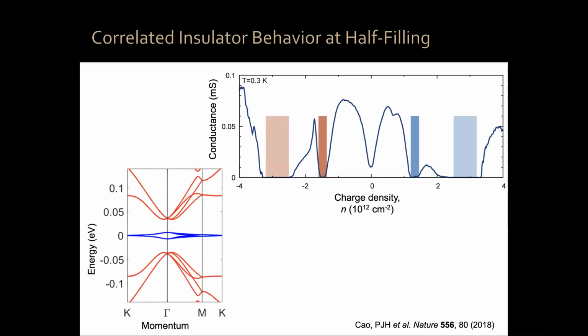So this is again the electronic structure. Remember that I told you that the number 4 would appear again. It turns out that in these black bands, starting from charge neutrality, to reach this region, you have to add 4 electrons per Moiré unit cell to the system. From charge neutrality, to reach this region, you have to add 4 holes per Moiré unit cell, or remove 4 electrons per Moiré unit cell. And so these black bands contain in total 8 electrons per Moiré unit cell.